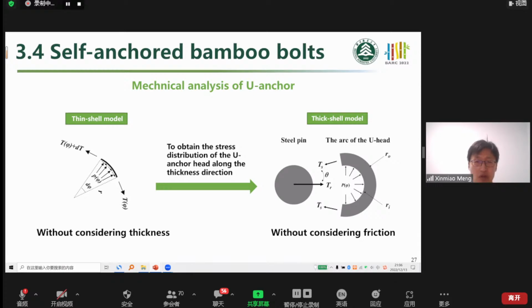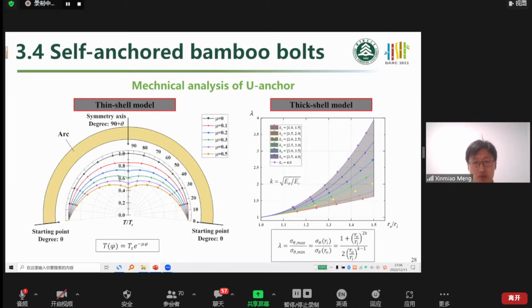But we know that for the thin shell model, because it didn't consider the thickness, we don't know the stress distribution across the thickness of the cross section. But for the thick shell model, we can obtain the stress distribution across the cross section, but we cannot consider the friction at the interface. So here are the results. We can get the stress distribution along the bolt and across the cross section.